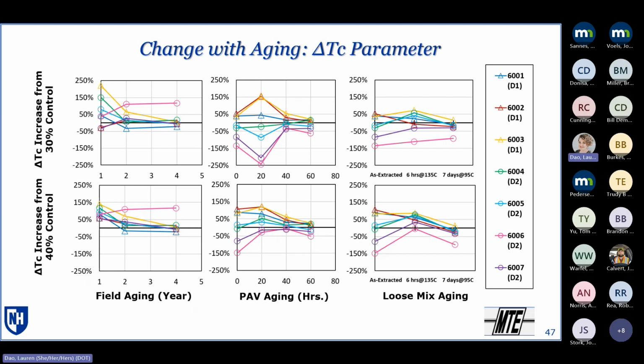Again, you can see here with the additional aging, especially as you get to those longer term aging, you're seeing these all collapse together and come very close to the controls. And the same thing with the loose mix aging, the as extracted, and then the two different long-term aging, with the 6 hours being less severe than the 7 days at 95 degrees C. So it's just a different way of looking at the data.